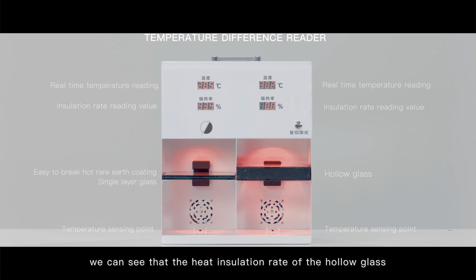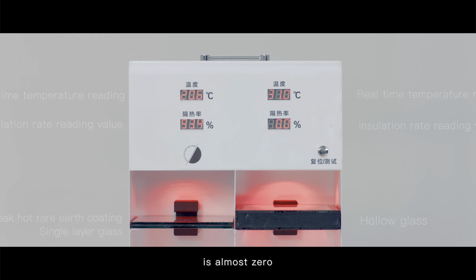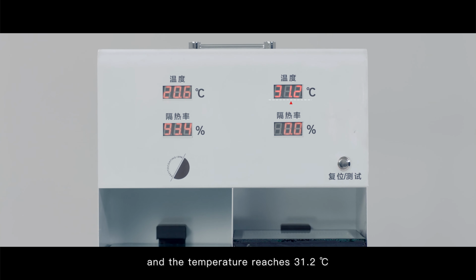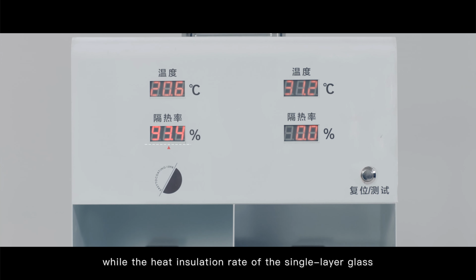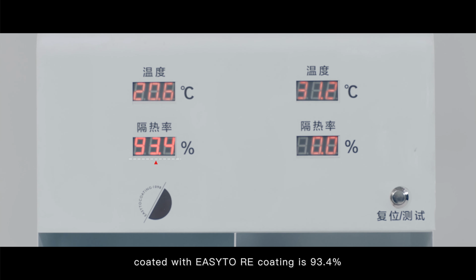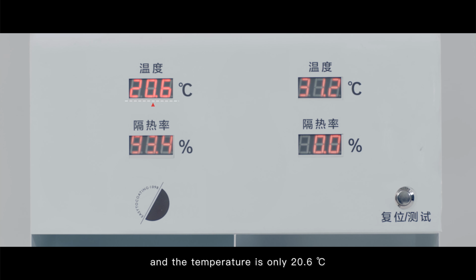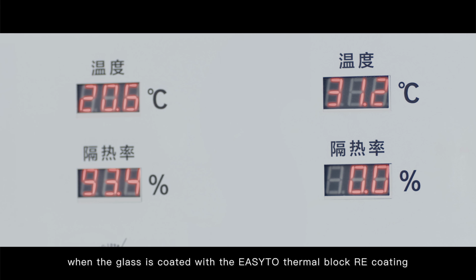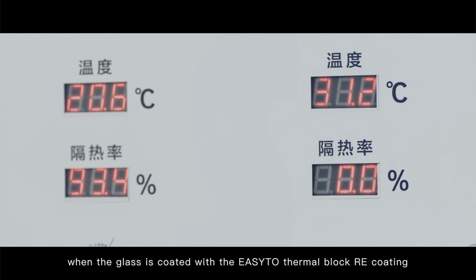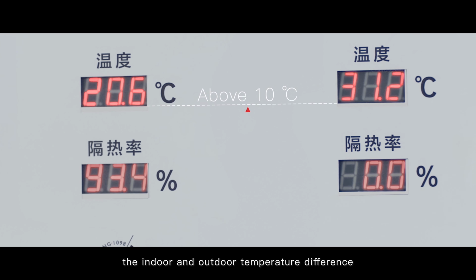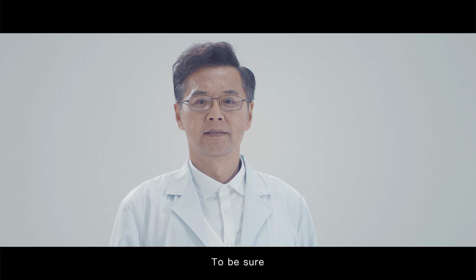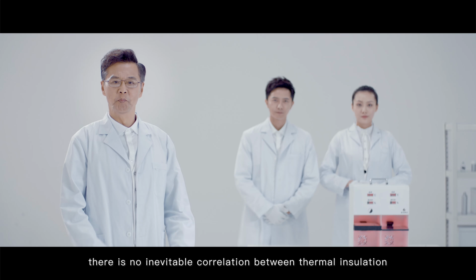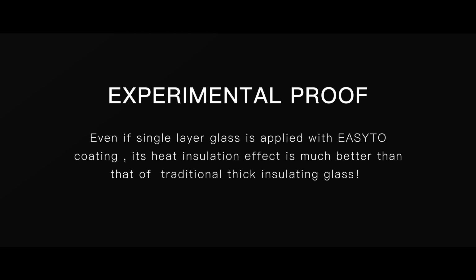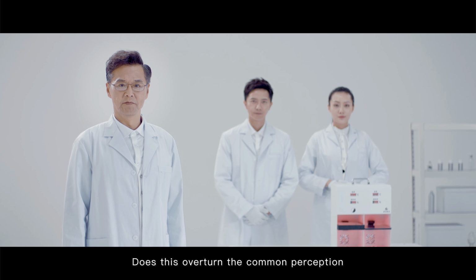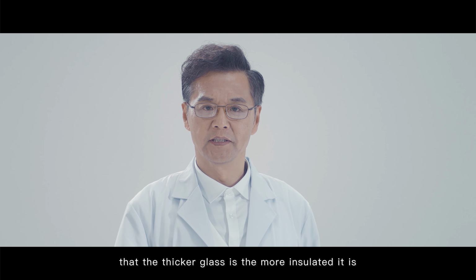1 minute later, we can see that the heat insulation rate of the hollow glass is almost zero, and the temperature reaches 31.2 degrees Celsius, while the heat insulation rate of the single-layer glass coated with EASYTO coating is 93.4%, and the temperature is only 20.6 degrees Celsius. That is to say, when the glass is coated with the EASYTO Thermoblock RE coating, the indoor and outdoor temperature difference can be as high as 10 degrees Celsius. To be sure, there is no inevitable correlation between thermal insulation or energy savings and glass thickness. Does this overturn the common perception that the thicker glass is more insulated than it is?